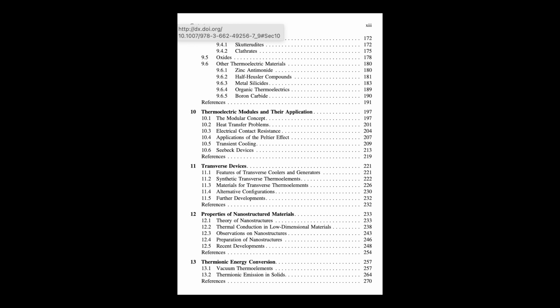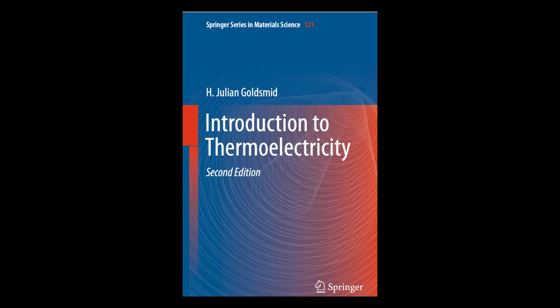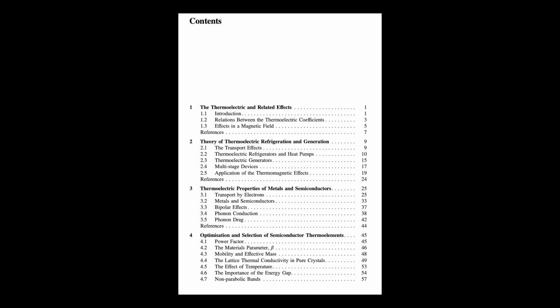Moving up in temperature, intermediate range generators. Yeah, mid-range, maybe a few hundred degrees C up to nearly 1,000 degrees C. Lead telluride, PbTe, and its alloys, and silicon germanium, SiGe alloys, are the main players. Used a lot in waste heat recovery and famously in those RTGs, radioisotope generators for spacecraft. PbTe is isotropic, same properties in all directions, high mobility. But ZT isn't amazing on its own. SiGe is studied a lot for high temp use, optimizing the Si:Ge ratio and doping.